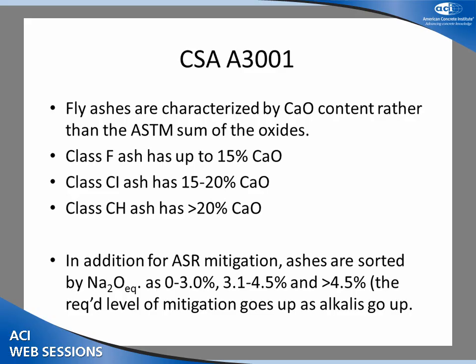They're often good technical ashes, good early setting times, good strength development, but they often are associated with some durability issues. We also sort, in terms of ASR, on alkali content, the equivalent alkali content. We consider anything up to 3% alkali as being low in terms of the ash. And then we have a second category, if you're up to 4.5%, you need more mitigation in terms of mitigating the ASR potential. And if it's above 4.5, you have to use testing rather than an expert system to prove it.